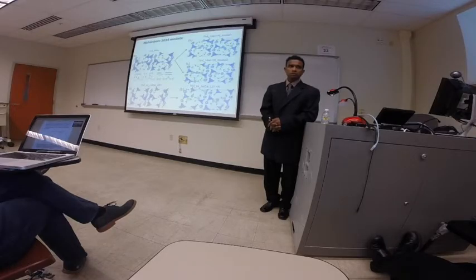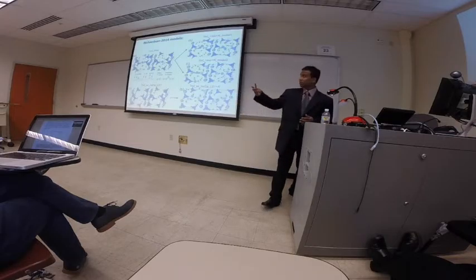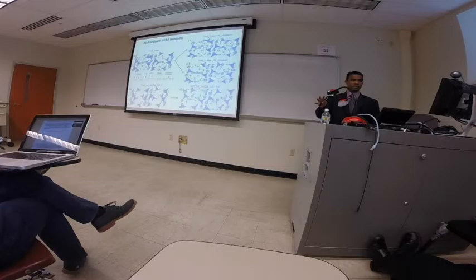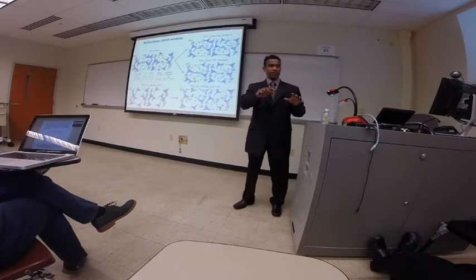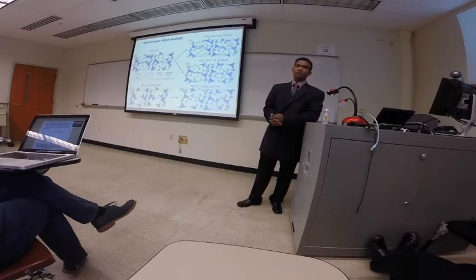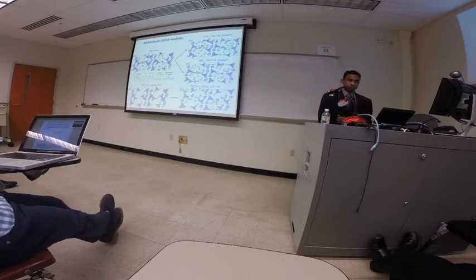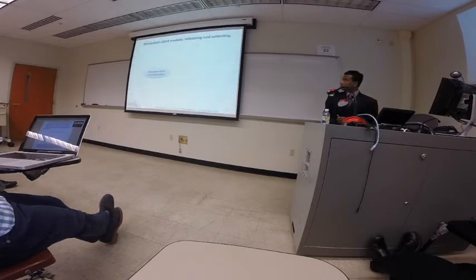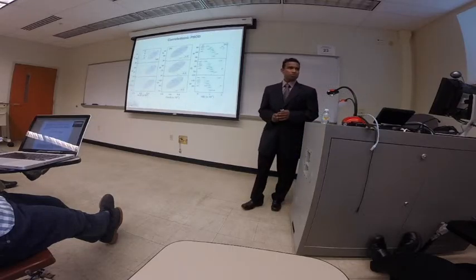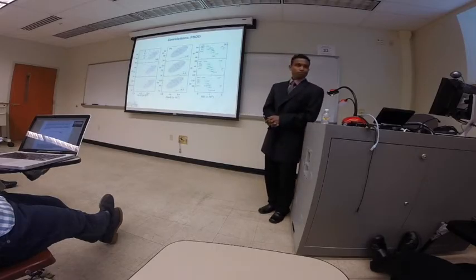Is there a way that you could imagine trying to account for that or bring that factor into your measurements? I think that's why we went into partial bond order density, to further dissect the total bond order density. Because total bond order density, as I showed earlier, did not correlate very well with mechanical properties. But partial bond order density, since it accounts for different species, gives, you had the little ovals on each of them, the hydrogen-oxygen one, the HB one, that one had the most elongated oval. But still, it kind of reduces down to, instead of one number, you have three numbers, and the number is sort of an overall thing.